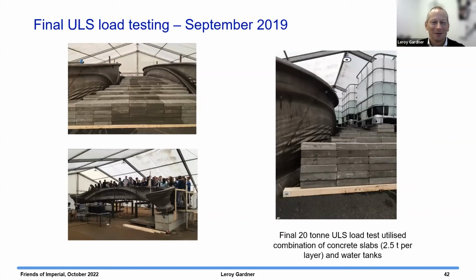So then the final set of tests was what you can see on the slides here. Loading came now from a combination of a lot of individual paving slabs, loaded up, roughly 2.5 tons per layer of these blocks, and 6 layers, and then water tanks on top of that. All of these blocks were placed manually by me and some friends, and took a while, and we didn't put them on randomly. We tried to put them on so that we achieved a uniform loading throughout the addition of these things. So the total load with all of the slabs plus the water tanks was about 20 tons. And that is beyond the total factored loading that would be applied to one of these bridges in practice, and quite a lot beyond what it would ever be expected to actually see in practice.